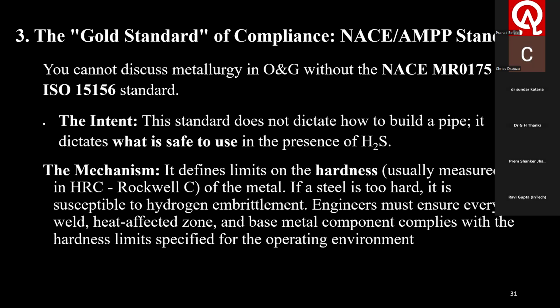What is the mechanism? It defines limits on the hardness, usually measured in HRC, Rockwell C, of the metal. If a steel is too hard, it is susceptible to hydrogen embrittlement, we know very well. Engineers must ensure every weld, heat affected zone, and base metal component complies with the hardness limits specified for the operating environment. It's a very important mechanism to be known to meet this intent.